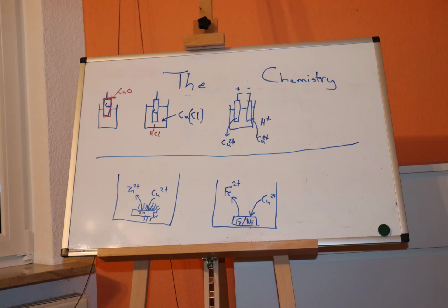But with a battery we can make it happen a lot faster, but we do have the problem that when the concentration of copper ions gets up too high, instead of making hydrogen at our negative electrode, which we would normally do, we start to use up the copper ions, and then we've just wasted energy. That's why I use an old 9-volt battery for this, because they're easy to get hold of and because they don't cost anything.